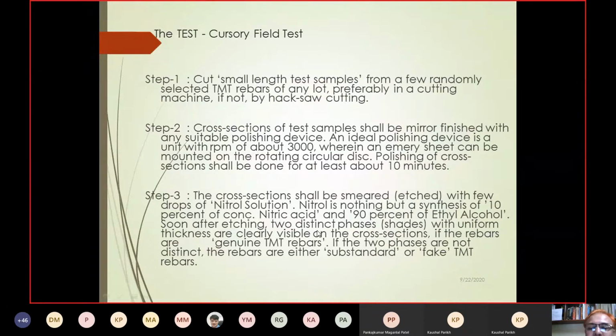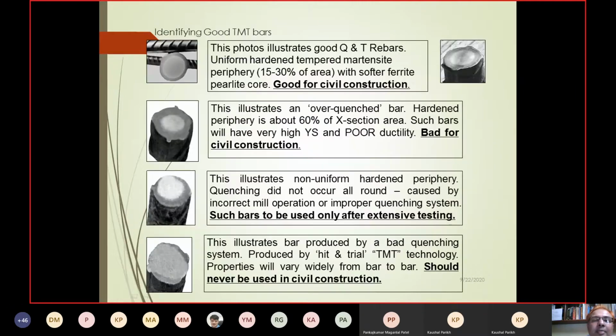Soon after, two distinct phases or shades with uniform thickness are clearly visible on the cross section. If the two phases are distinct, the rebar is a genuine TMT bar. Otherwise the rebar is a substandard or fake TMT rebar. What is the actual good rebar? See here.